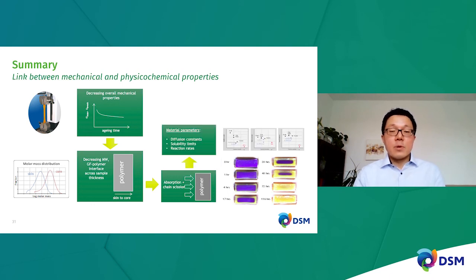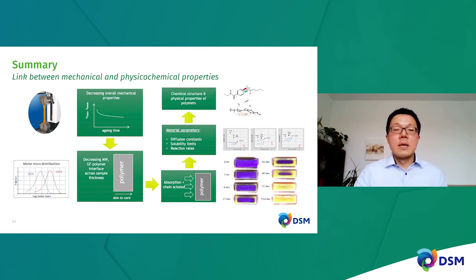which is related to these three important parameters that I've been discussing about, so diffusivity, solubility, and the reaction rates. So if all these parameters are low, then you don't need to worry about the degradations. But if they are pretty high, then you will see the impact in terms of mechanical performance. And these three parameters are linked to the chemical structure and physical properties of the polymer itself. So the intrinsic properties of polymers usually link towards their parameters and eventually to the mechanical properties.